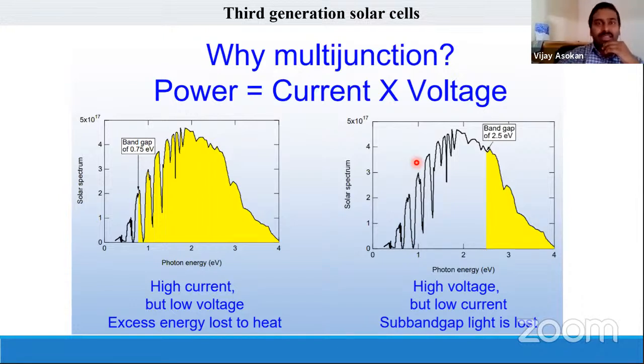We need to be more particular about this, as more multi-junction solar cell devices are made using those third generation solar cell materials. So here, if you're considering a band gap of 0.75 electron volt, then all the photon energy which exceeds this band gap can be utilized. That's what we keep on seeing, right? So these things are possible here, but when we have a material band gap of around 2.5 electron volt, then only energy exceeding this can be utilized. So in a multi-junction, we can combine these different band gap materials, so we can utilize all such incident energies.